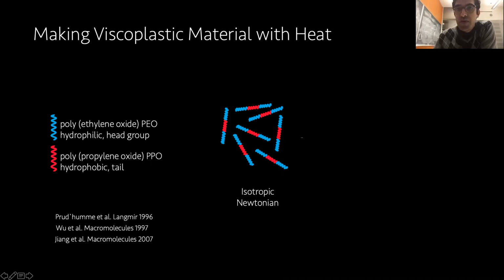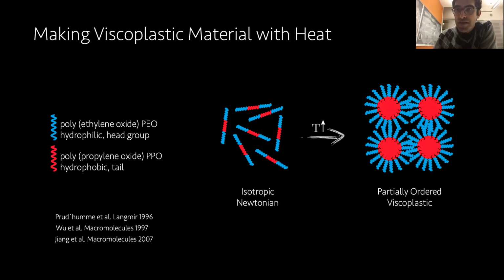What is super interesting about this polymer is that if you heat it up, they form micelles, and if the micelle concentration is high enough, they pack, and then they form a viscoplastic material. It's super counterintuitive if you don't know anything about them. Typically, if you have a polymeric solution and you heat it up, the viscosity goes down, but this one is a magical one. You heat it up, and it suddenly turns to a viscoplastic, yield-stress fluid.